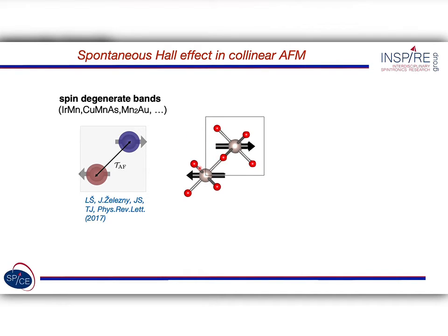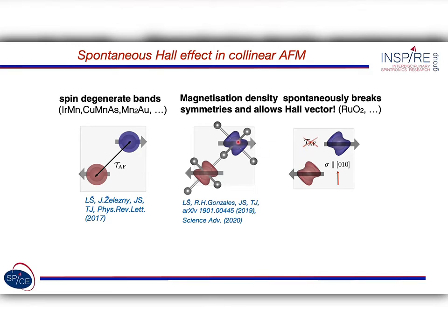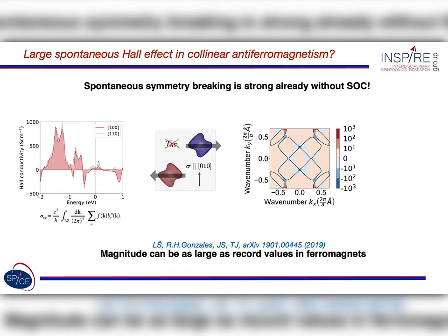Here is an example of a material where you have these hexagonal cages, reorienting and breaking the symmetry for the spin densities. As you can see, you don't have this effective time reversal symmetry when you switch between the two, because if you do the inversion symmetry point and then time reversal, you will not end up with the same spin density structure. You can do the calculation here and obtain a Berry phase calculation with spin-orbit coupling. And without spin-orbit coupling, of course, it would be zero.